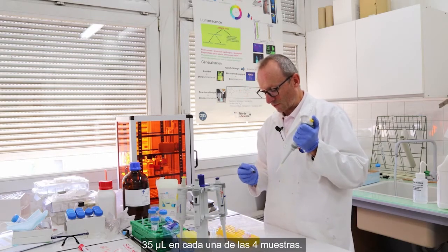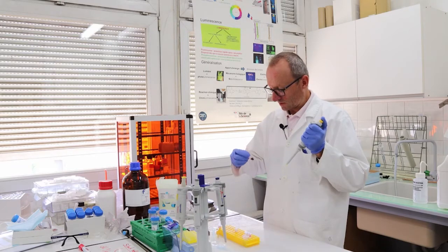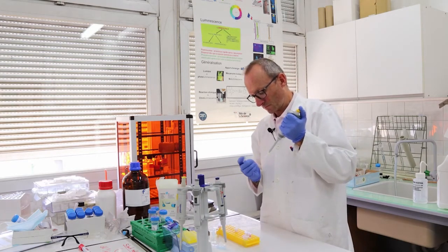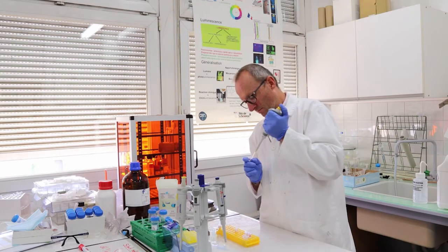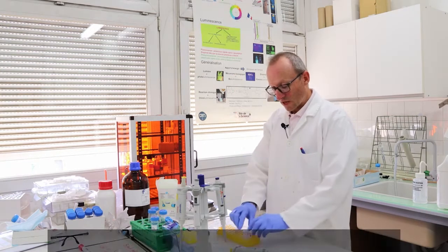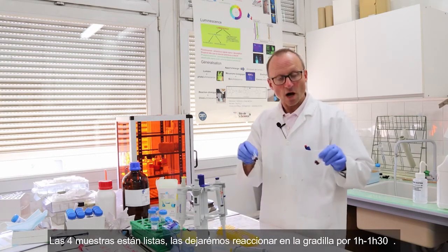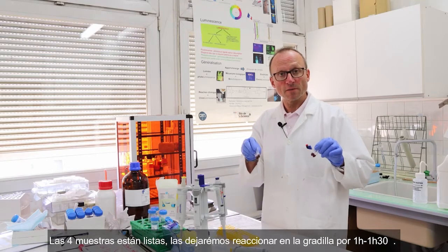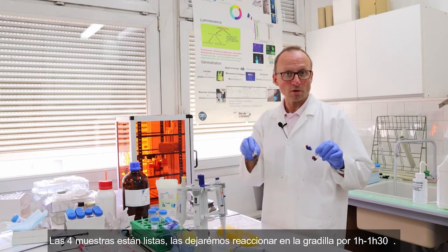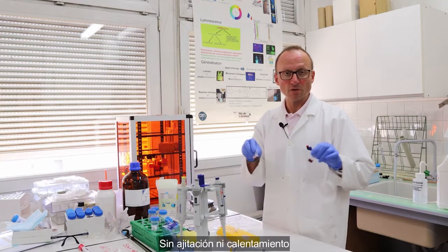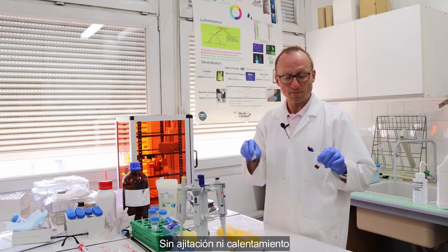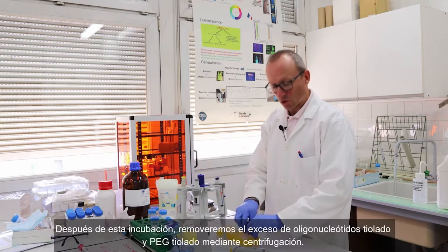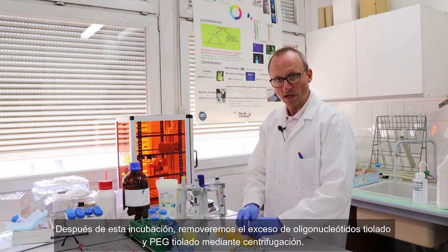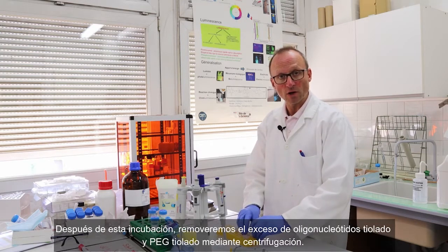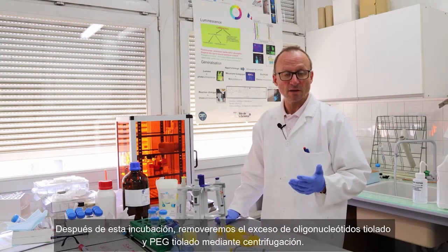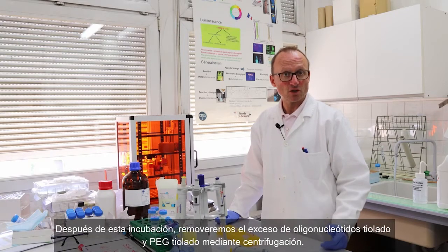In each of the 4 samples. So now the 4 samples are ready. We will leave them on the bench for 1 hour up to 1 hour 30 without any stirring at room temperature. And after this incubation, we will remove the excess of thiolated oligonucleotide and thiolated PEG by centrifugation.